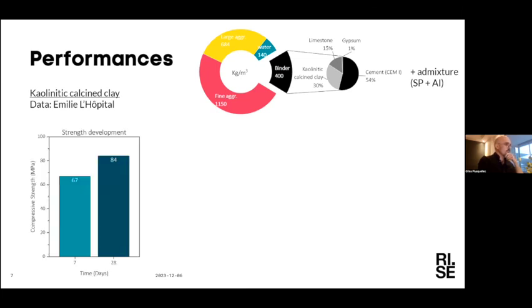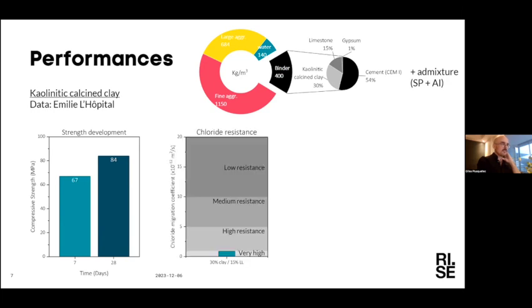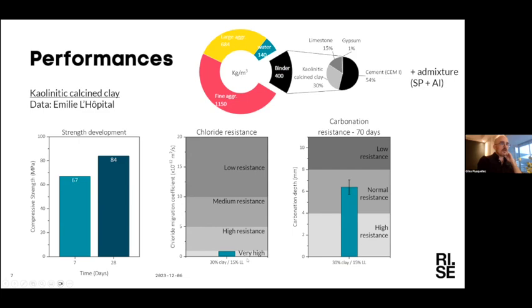So first for the strength. On the concrete cubes at 28 days, we can reach a strength of up to 84 megapascal, which is not bad at all, quite high even, I have to say. And we looked at some durability resistance as well in accelerated lab tests. Here's the result for the chloride resistance, and we place ourselves in what is considered to be a very high resistance material. And for the carbonation here, we will be in a more normal resistance area.